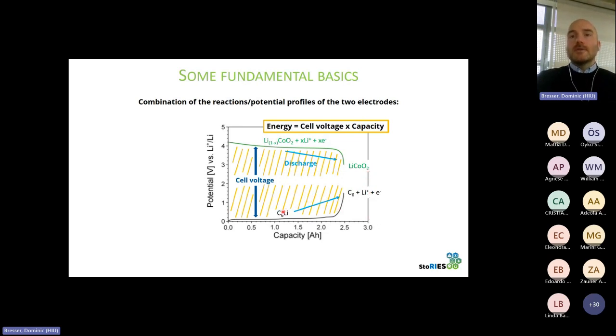Or if we just reduce the voltage and basically shorten the capacity, and especially considering that graphite is a wonderful material, right? You see it's very close to 0 volts, 0 versus lithium plus lithium, meaning that it's hard to get even lower than that, except if going for metallic lithium, while apparently we would need to increase the capacity at such low voltage to really make a great impact on the eventual energy.